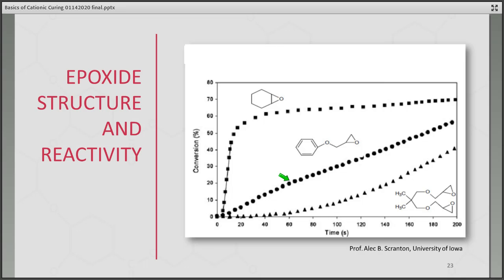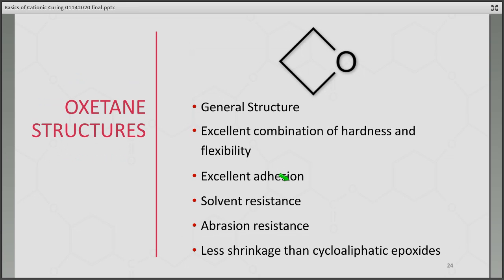On this chart, we could see perhaps a more interesting or a little bit different example of the epoxide structure and its effect on reactivity. This is work done by Alec Scranton, University of Iowa, and we see here he compared cycloaliphatic epoxide with this glycidyl, and then with just a simple aliphatic system. You can see how rapidly the cycloaliphatic epoxide will react with the cation, and you get conversion much quicker than either the glycidyl or the aliphatic system. So this illustrates very clearly why cycloaliphatic epoxides are the workhorse in UV curable cationic systems.